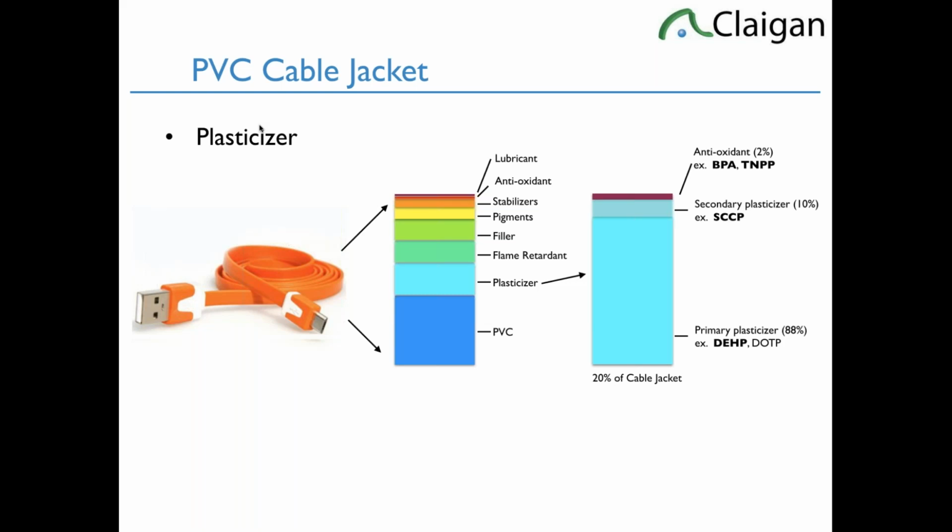You put two flexible PVCs next to each other, or even a flexible and a rigid, the phthalate from one will migrate into the other. It's fundamentally liquid. The secondary plasticizers, so SCCPs, make orthophthalates more compatible with the PVC, so less likely to migrate out, and you don't need as much of it.